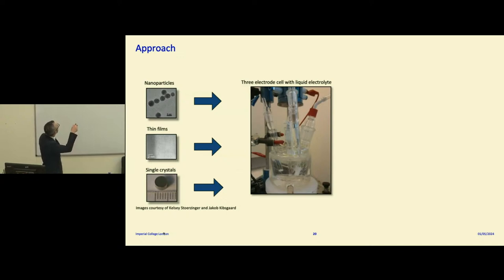These are typical size nanoparticles, 5 nanometers across. Or we could look at oriented thin films, even single crystals, that's 5 millimeters across. It's quite interesting to consider the length scale: there's about a million times difference between the size of these particles and this single crystal. Whereas in an actual device, you often use a polymeric solid electrolyte, often what we use instead is a liquid electrolyte, and we rotate the electrode to stir the solution and bring reactive gases to and from the electrodes we're studying.